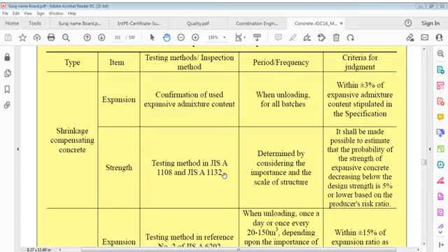For expansion, the testing method or inspection method is confirmation of used expansive admixture content, and for strength, a strength test. Period or frequency is, for expansion, when unloading for all batches, and for strength, determined by considering importance and scale of structure. Judgment is within plus minus 3% of expansive admixture content stipulated in the specifications, and for strength, it shall be possible to estimate that the probability of strength of expansive concrete decreasing below design strength is 5% or lower based on producer's risk ratio.